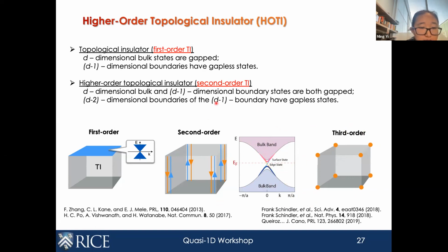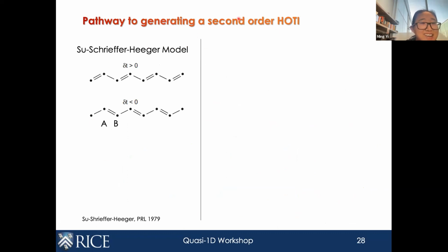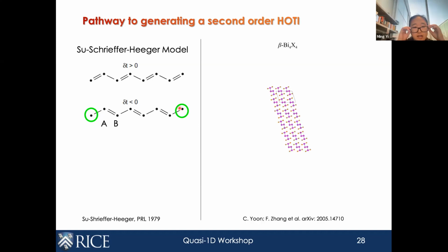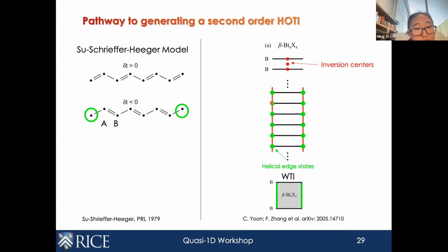I'm thankful that I'm following Fan because here I also just recapture what he has already motivated. We can understand the pathway to generating a second order higher order TI from the SSH model, where at half filling one can have dimerization, but there are two ground states, one of which will leave edge modes here. And so we carry this analogy to the bismuth halide systems that we have here. We can think about each layer as one of these dots. And in the simplest case of no dimerization, as Fan has already patiently explained, there's an inversion center, which indicates that you have edge modes on the two edges.